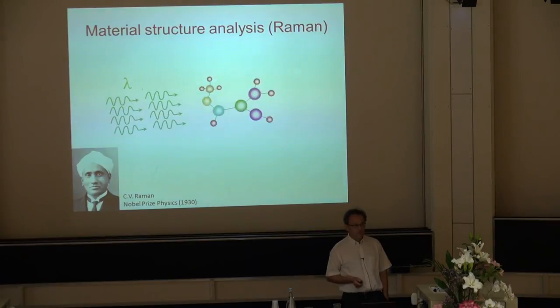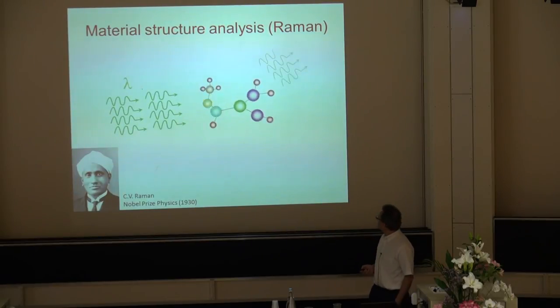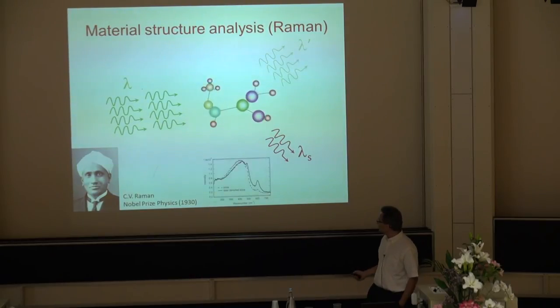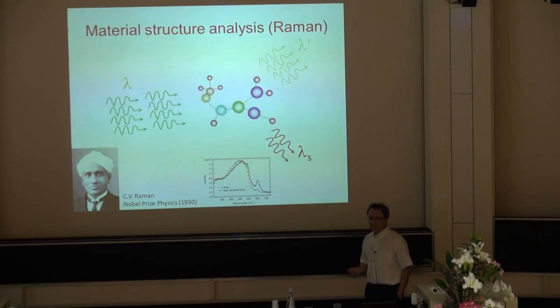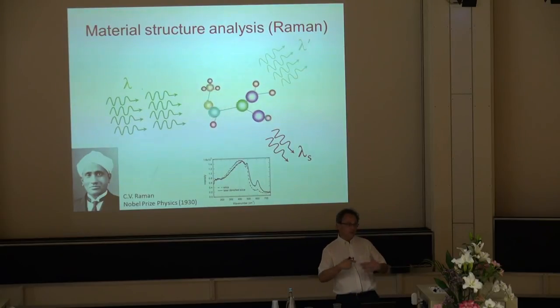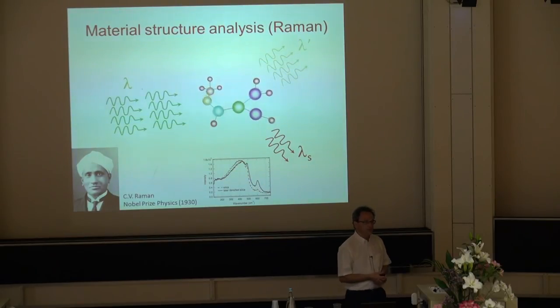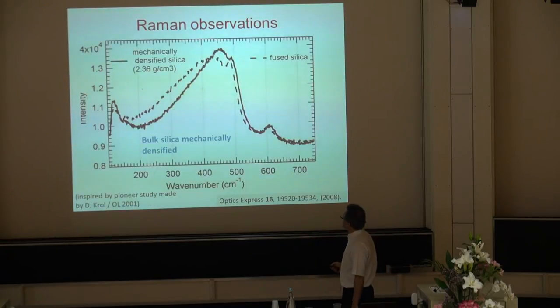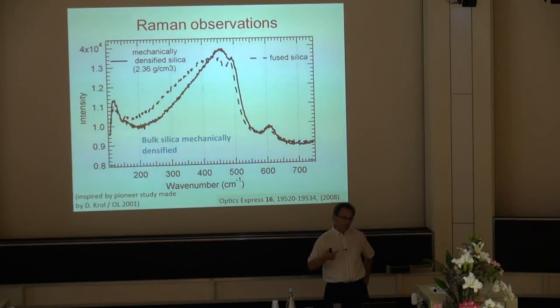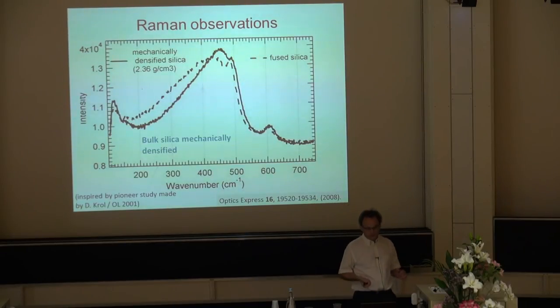Now, if you fire a laser light on that, then you will have some scattering, and if you observe this particular scattering, then you get a spectrum. That is telling you something about how the structure is in the material. So then you can infer what kind of structure the material has. We use that a lot to examine what happened after the laser exposure.